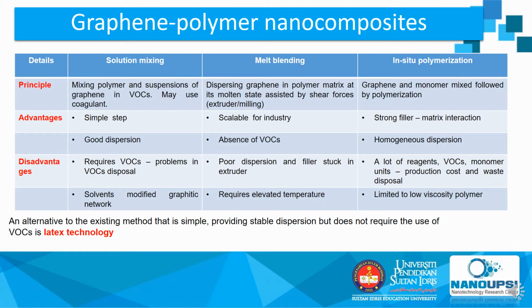Therefore, numerous techniques have been introduced to prepare graphene polymer nanocomposites, for example in natural rubber latex: solution mixing, melt blending, and in situ polymerization. However, these techniques have disadvantages. For example, solution mixing requires volatile organic compounds through the process, and melt blending provides poor dispersion and filler stuck in the extruder.